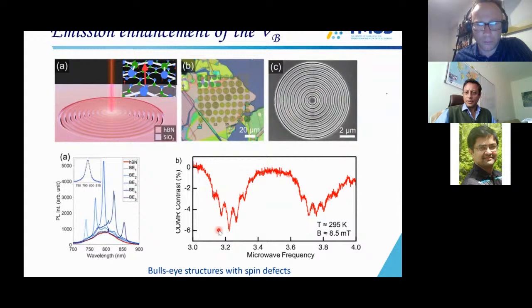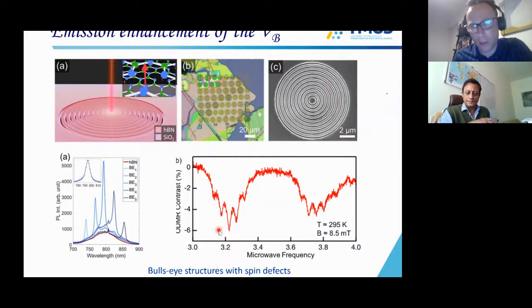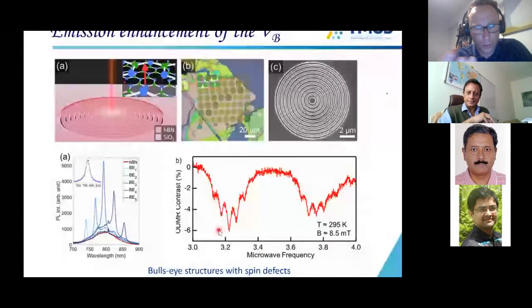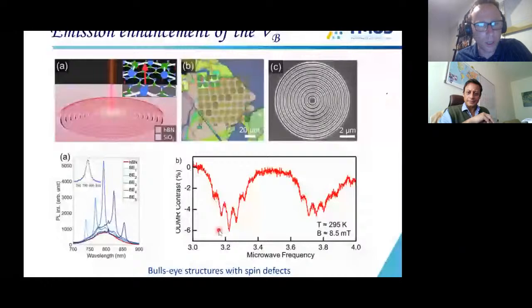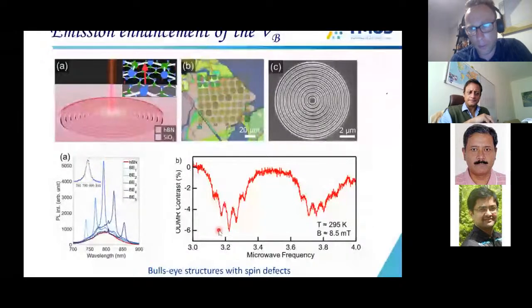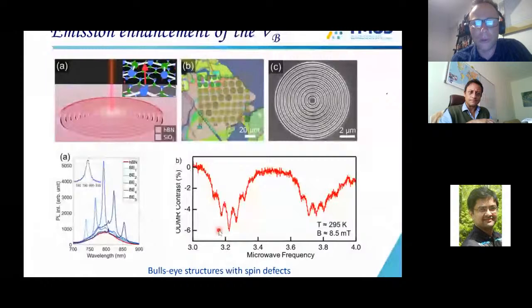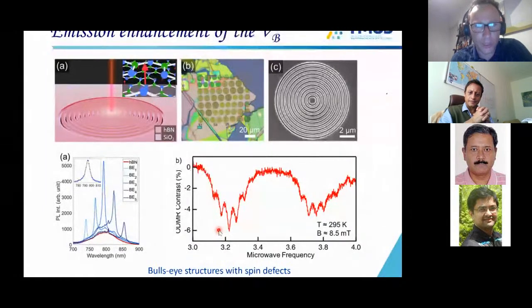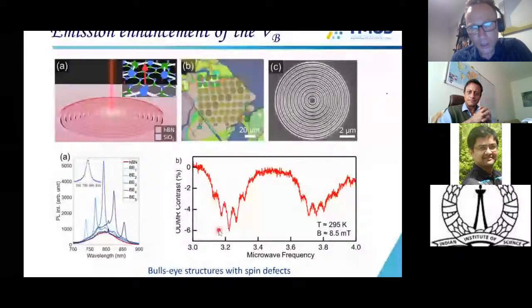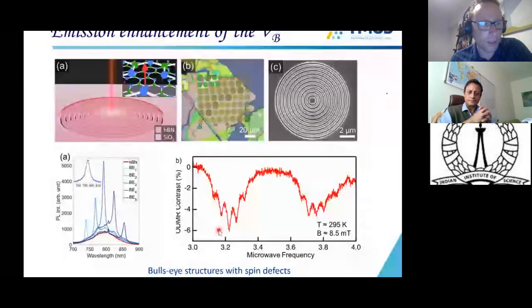Great, thanks. I'll take one more question, and that is from Dr. Rajesh Vinayar. Is there any natural defect present in hBN, or do we need to create them by using ion implantation? That's a very interesting question. Originally, we found that single emitters occur naturally. You only need to anneal. So we took just commercial powder of hBN and annealed, and you have plenty of defects occurring naturally. The reason they occur naturally is because hBN is grown under high temperature conditions, always with a carbon precursor around it. Even if the carbon is not introduced intentionally, it's always there, simply because that's how it grows. So you will always have naturally occurring defects in hBN.